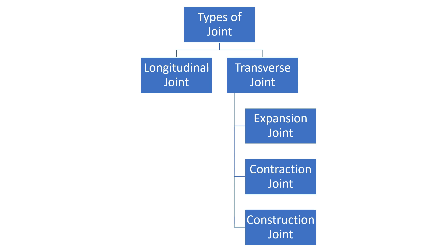The joint provided in longitudinal direction as seen here is known as longitudinal joint. When any dimension of this pavement exceeds 4.5 meters, shrinkage cracks generally develop in the pavements supported on the base course during the initial period of curing. So in pavements of width more than 4.5 meters, there is a need to provide a longitudinal joint.